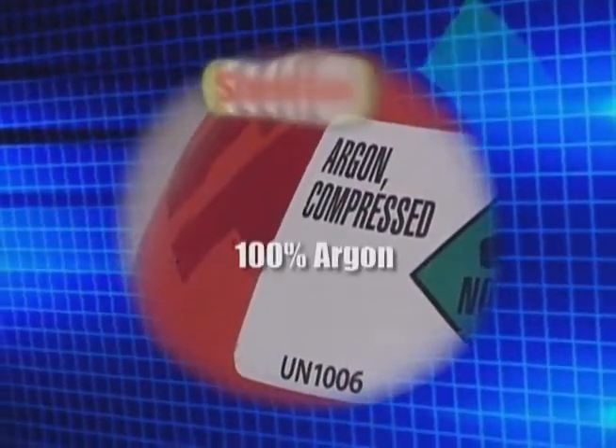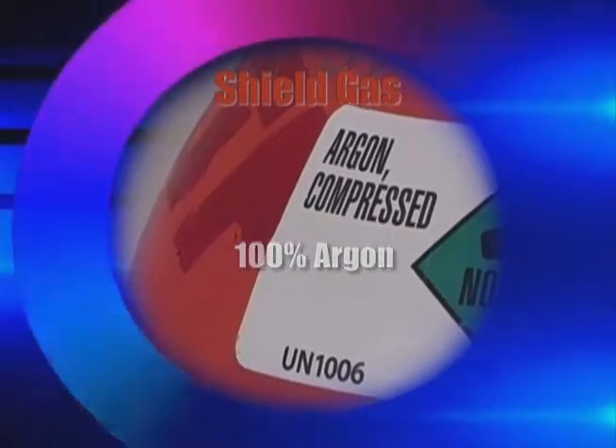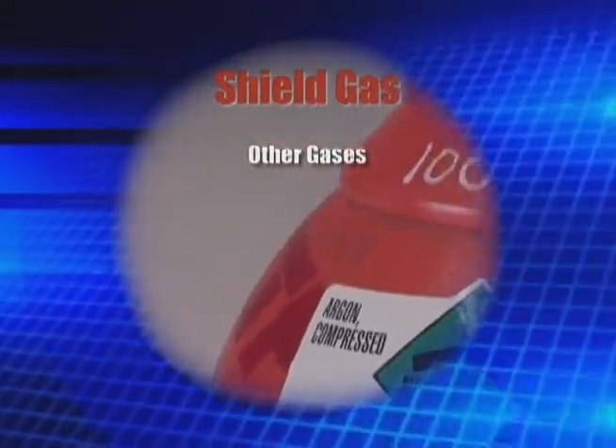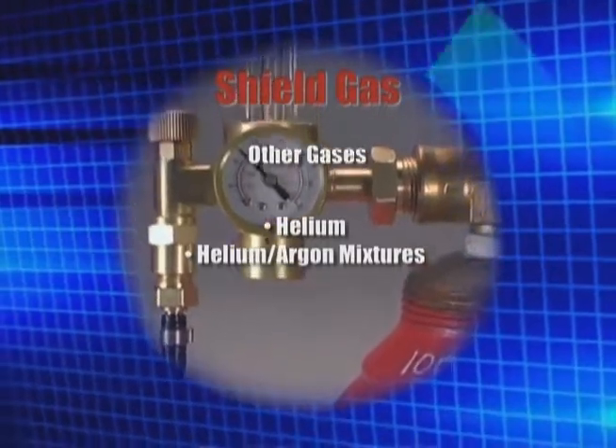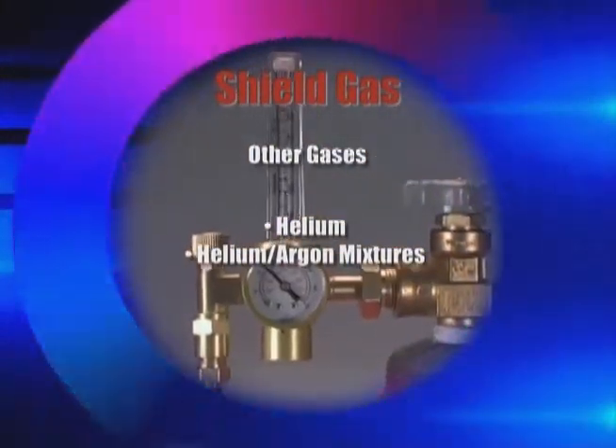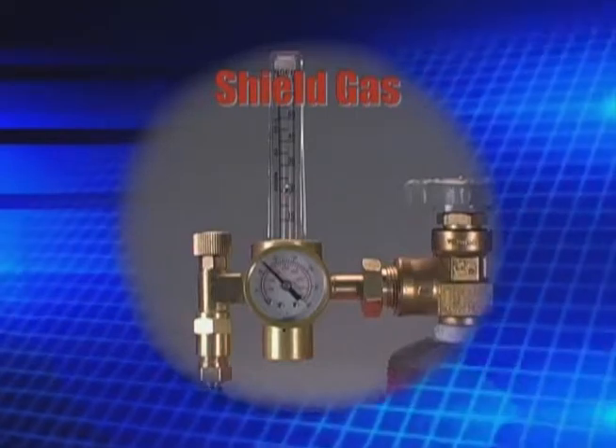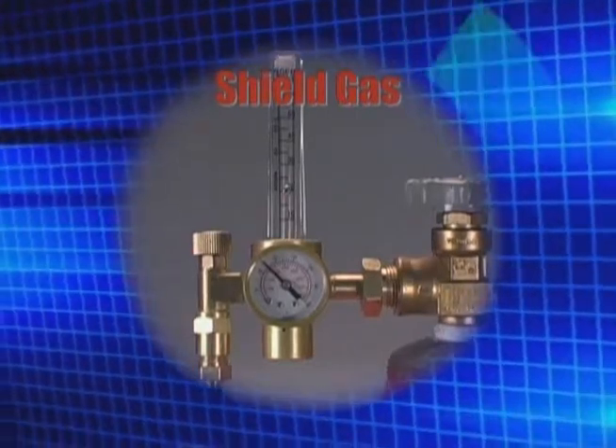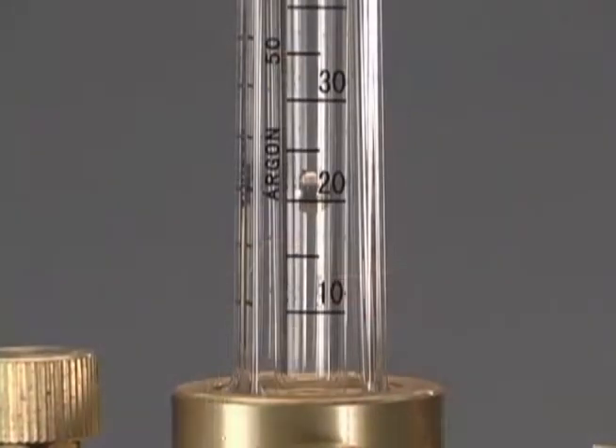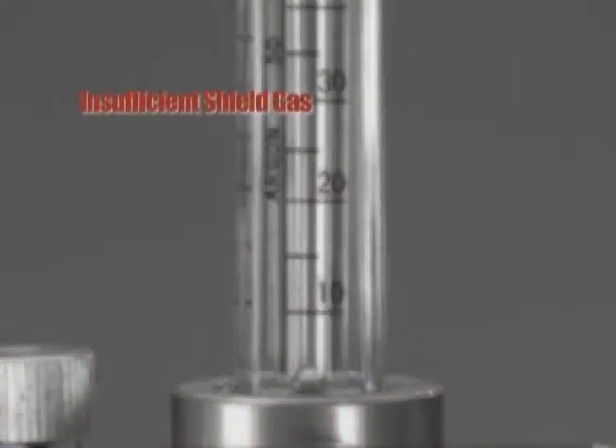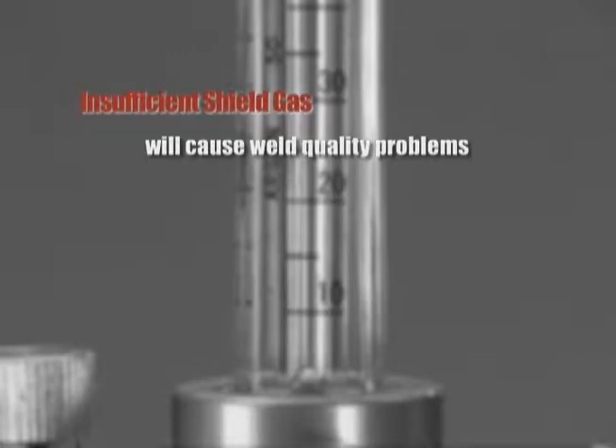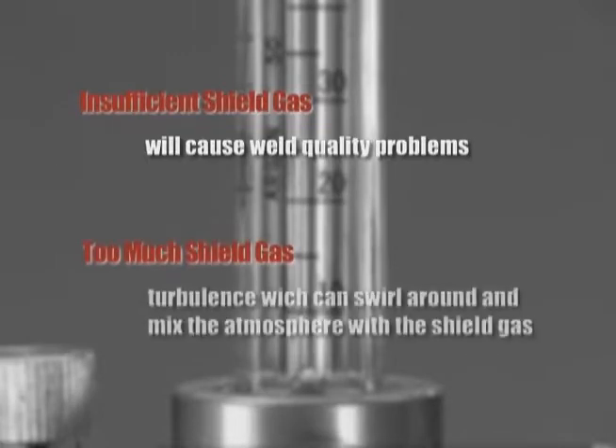In this video, the shield gas that we will be using is 100% argon. There are other shield gases available for TIG welding, such as helium and helium-argon mixtures, but they go beyond the scope of this video. Generally speaking, the flow rate will be 15 to 25 cubic feet per hour. This will be dependent on the diameter of the cup and the amount of tungsten stick-out. Not enough shield gas will cause weld quality problems, and too much shield gas can cause turbulence, which can swirl around and mix the atmosphere with the shield gas.